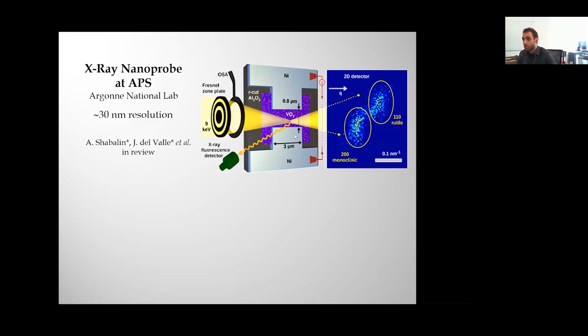So what we did is the following experiment. We took a device very similar to the one that I showed you. You have here a representation. It's a VO2 film in this case with two nickel electrodes separated 100 nanometers between them. And we took them to Argonne National Lab, to the synchrotron there, and there they have an X-ray nanoprobe that can focus the X-ray beam down to a 30 nanometer spot. We did this in collaboration with the Shpyrko group.